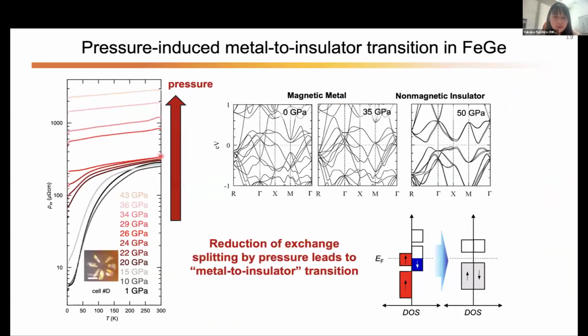This is the result. So first of all, we observed the signature of a pressure-induced metal to insulator transition. As you see, when we increase the pressure, the resistivity is enhanced by two or three orders of magnitude. And this behavior is also corroborated by the DFT calculation. This is a very rare case because usually pressure turns an insulator to a metal and even a superconductor, but this is the other way around, because we are turning the metal to an insulator. And this is because the pressure reduces the exchange splitting of the band structure. And if the Fermi energy is located at the band gap, the system becomes an insulator. So we observed a very rare case of a pressure-induced metal to insulator transition.